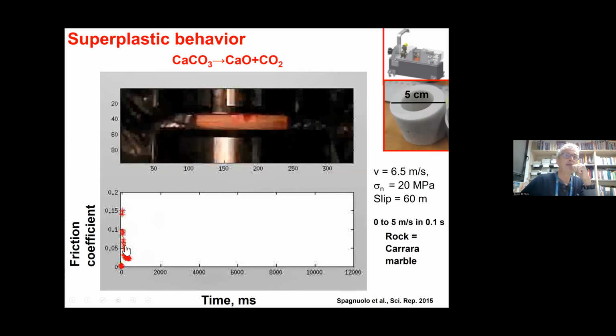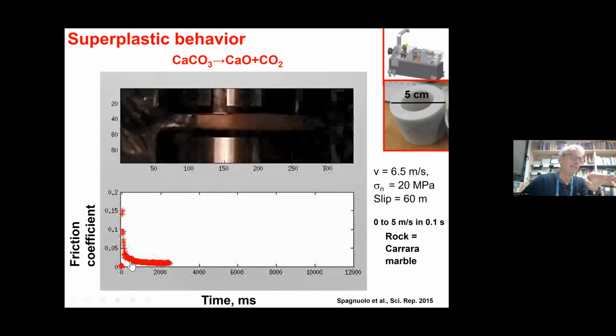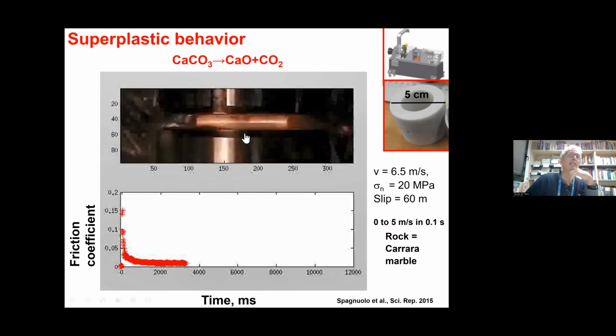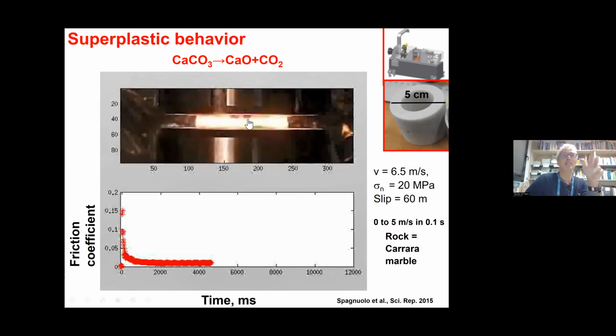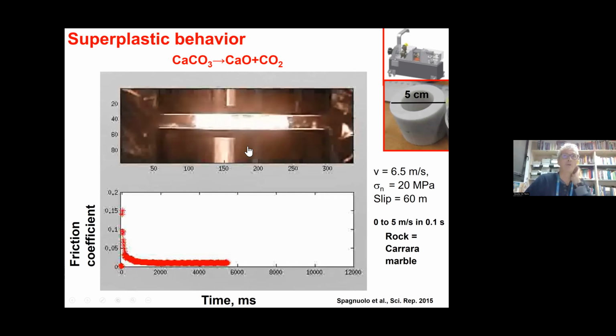So there is a very rapid drop in friction. These are milliseconds. The target slip rate was quite high, 6 meters per second. The stress, 20 megapascal. You can see that after a few hundreds of milliseconds, don't worry, it goes. A few hundreds of milliseconds, friction is about 0. So there is a full lubrication. However, there is no movement of the piston here. Basically, there is no expulsion of material, very little, but then the temperature increases. This is not natural anymore because the displacement is enormous, 60 meters probably, and you can start to see sort of lights coming out from the sample.